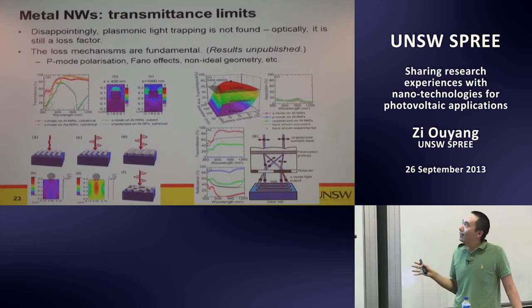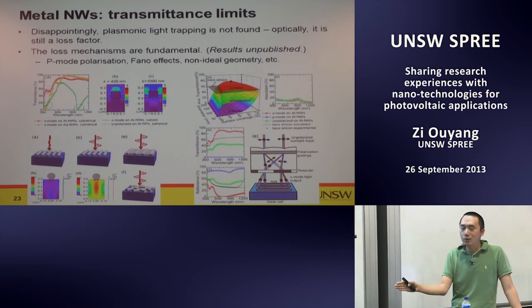Disappointingly, we never find plasmonic enhancement on the nanowires. It's different from nanoparticles. So then we look into what's happening, and we find polarity. Polarization is the biggest harm. So we have very high S mode enhancement, but P mode is almost nothing. P mode means the electric field of the light is parallel with the nanowire. So it basically just blocks the light.